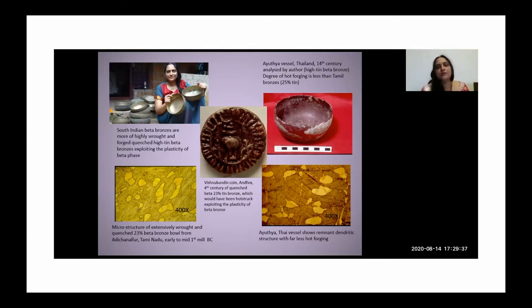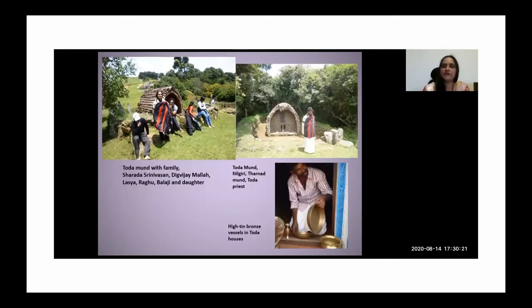Now, another example where this plasticity of beta bronze seems to have been used in a very interesting way is, you're looking in the center at a coin of the Vishnukundin period from the Andhra region. And I had managed to analyze that, and that is also found to be of quenched beta 23% tin bronze. So here what they seem to have done is they seem to have hot struck it, in that temperature range of the plastic beta formation, because it is quite plastic. So this coin was not, the design has not been made by casting it, but it has been hot struck. And I think this is one of the very rare examples we have of the use of beta bronze in coinage. So there are certain distinctive aspects to this tradition, which had survived for many years.